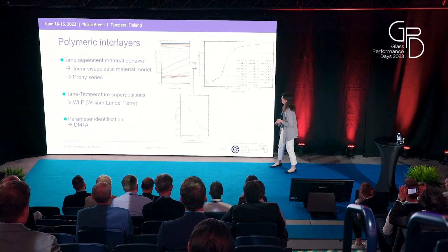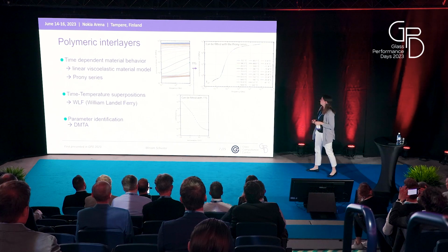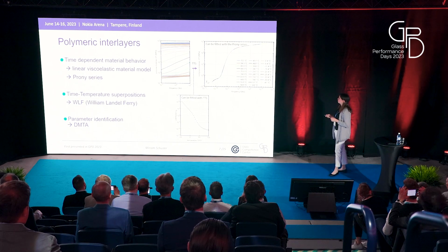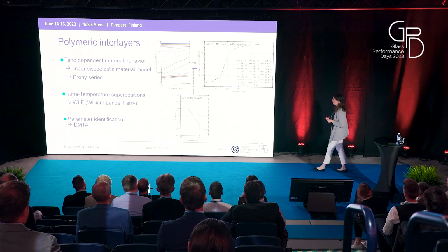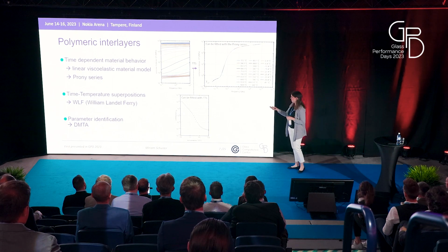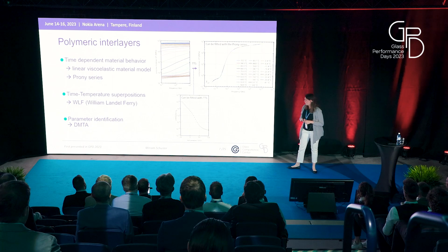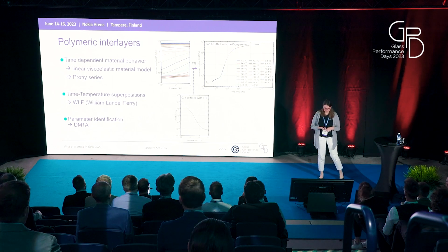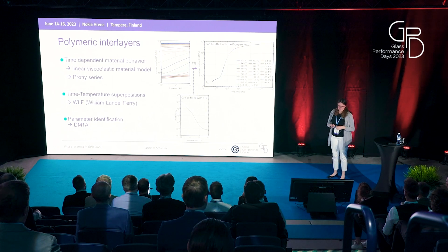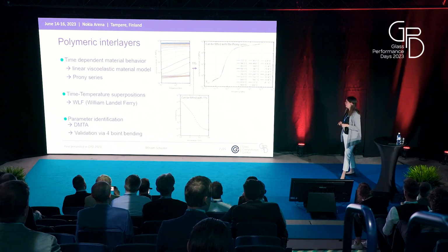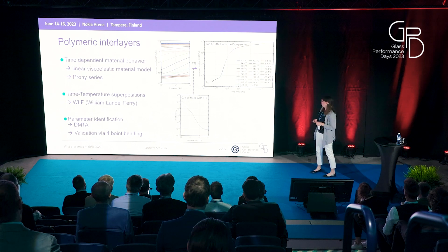And now we can use the master curve and fit the Prony parameters to this curve, and we can use the shift factors and determine the parameters of our time-temperature superposition principle. When this is done, we need a validation, and therefore often 4-point bending tests on laminates are performed.